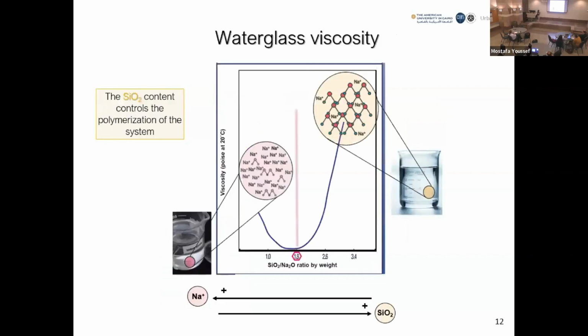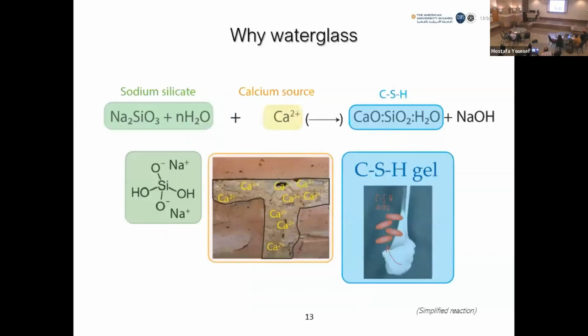So here, in a schematic way, I reported the trend of how viscosity changes as a function of the quantity of sodium to silica. It's important to keep in mind, as I told you, that for me it's important to have a material with a low viscosity, but at the same time it's also important to have a material which contains enough SiO2. Why is that? Because I would like to use this kind of reaction in my masonry in order to create CSH, which, as we all know, is the main reaction product after the hydration of Portland cement, and is able to give strength to the cement. And so I would like to recreate the same reaction also in the old mortar.